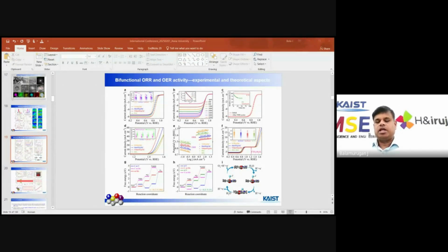After confirming from the three electrode systems, we have fabricated the metal air battery. You can see the metal air battery, when we fabricate the commercial one, we have to mix a 1:1 ratio of commercial platinum carbon and iridium oxide. But in our catalyst, only our catalyst is used as both the ORR and OER catalyst, in the dual function, because of that we call it bifunctional activity. So the peak power density is almost 1.5 times higher than the commercial catalyst, and this is also compared with the recently reported materials. It is a higher peak power density, and the practical applicability may be proved by the glowing series of LED, and the specific capacity is very high compared to the commercial catalyst.